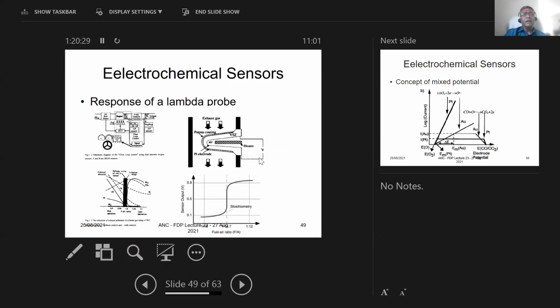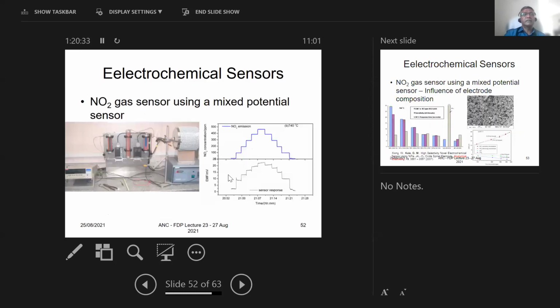But we did some studies on using these specific materials for nitrogen oxide gas sensing. And you can see that this is the trace of change in concentration of nitrogen dioxide going up and down. And this is the trace from the sensor, which is very good. It matches very well with the mass flow controller trace, where we have stepped up the composition of nitrogen dioxide in the gas mixture, and here stepped down. While stepping up, the sensor response is very quick, and it gives rise to a stable response fairly quickly and consistently in both directions, stepping up the concentration and stepping down the concentration.